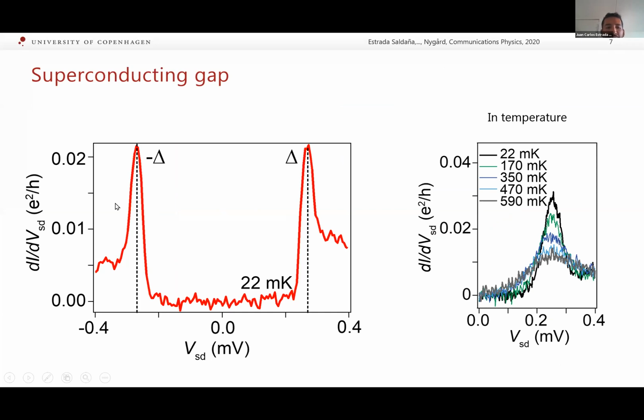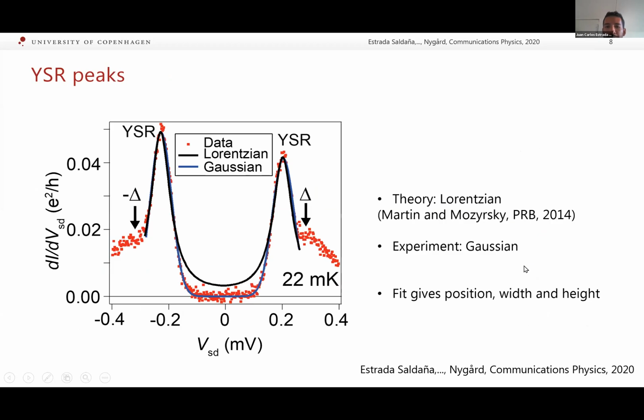And this is a measurement of differential conductance versus source-drain voltage. And this shows that the gap is quite hard. And these are the coherence peaks at the energy delta. But as the temperature is increased, this is a temperature dependence measurement, the delta peaks decrease in conductance. They flatten out a little bit. They stay constant in bias. They don't shift. And the gap gets filled by conductance. So the gap gets a little bit soft with temperature.